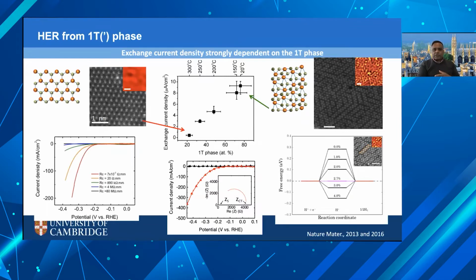for hydrogen evolution reaction. And so the main point that I want to make is that if you plot the catalytic activity, that is the exchange current density, as a function of the 1T phase concentration, and I explained to you in the previous slide that we can tune the 1T phase concentration by tuning the chemistry of synthesis, but also by annealing the as-exfoliated samples. And so we can tune the 1T phase concentration, and what we can see is that the exchange current density, which is an indication of the catalytic activity, increases by an order of magnitude.